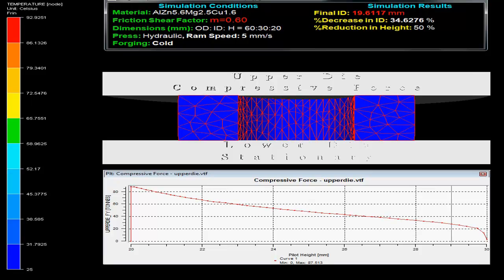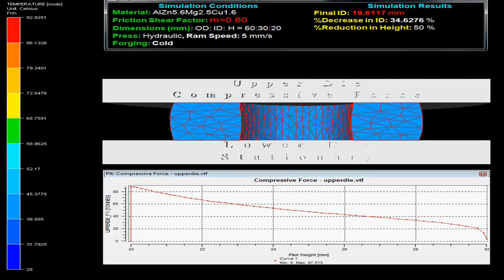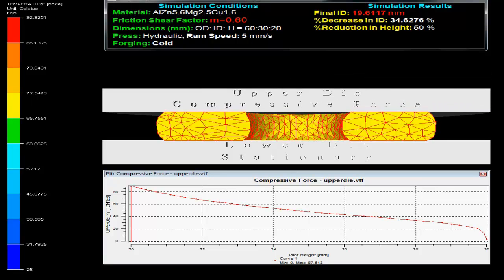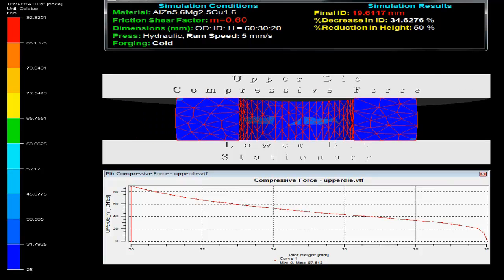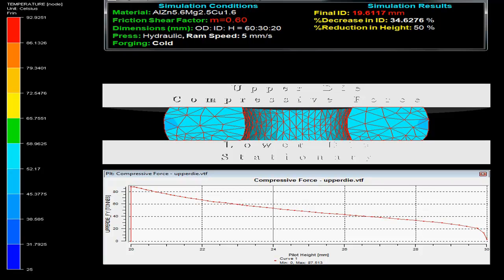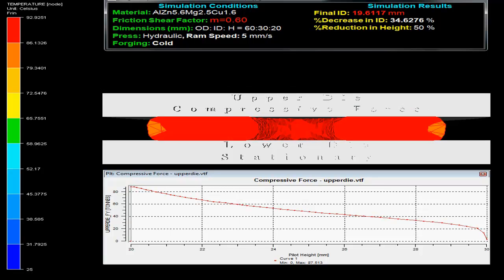The simulation results displayed on the top right show the final inner diameter as 19.61 mm, with a decrease in inner diameter by 34.63% at 50% reduction in height.